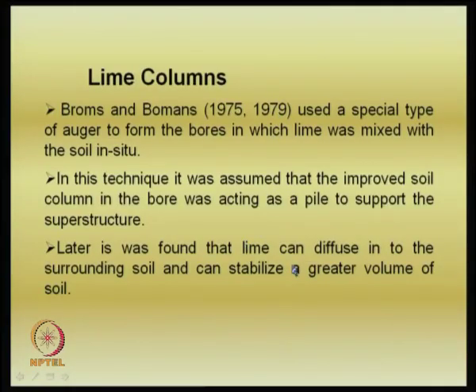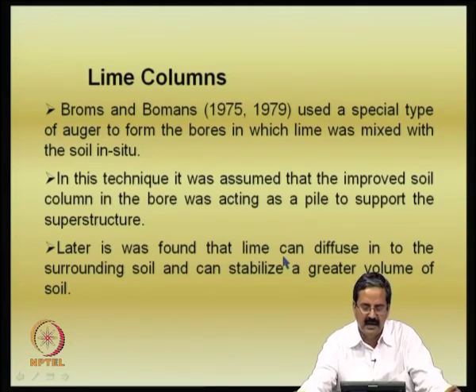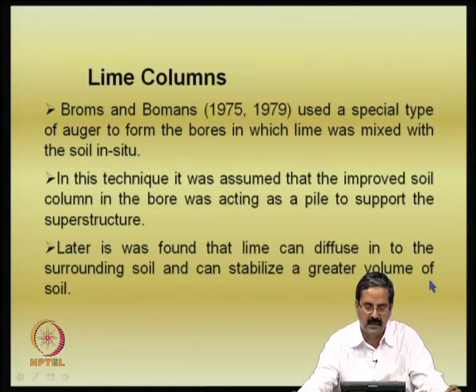People have also observed that it is not just about treating it as a pile. In fact, lime can diffuse — because knowing the permeability of the nearby soil, diffusion takes place and the lime can stabilize a greater amount of soil. People have studied a lot of work on diffusion of lime in soils, in places like IIT Madras and IISc. By creating lime columns and studying the concentration of calcium ions, it was found that with time the concentration of cations also increases next to the lime column.